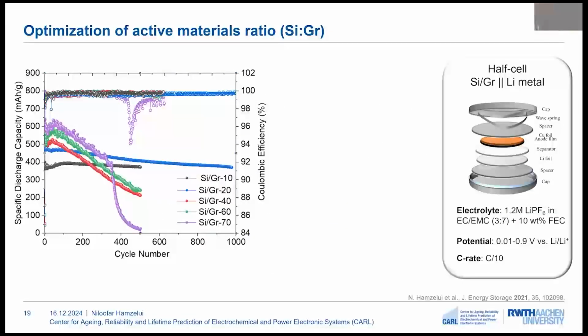After the anodes were prepared, they were assembled in coin cells against lithium metal, and the electrochemical performance of the cells was investigated. In this graph, we can see the capacity versus cycle number for different electrodes with 10, 20, 40, 60, and 70 weight% silicon. And as can be observed, by increasing the amount of silicon, we see less stable cycling performance and a more rapid capacity loss.